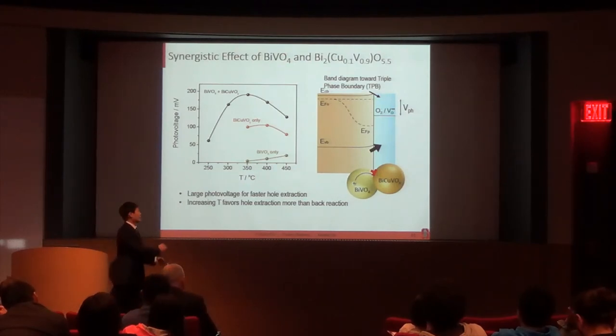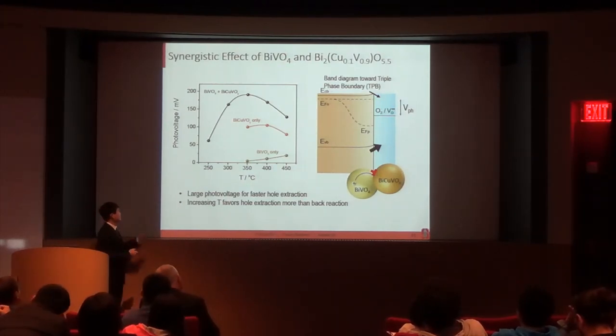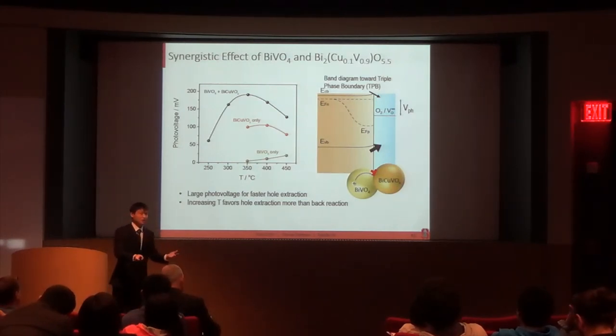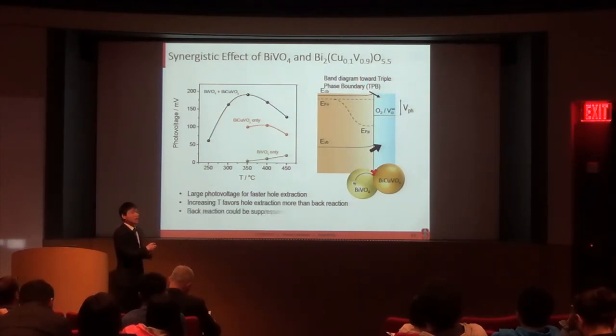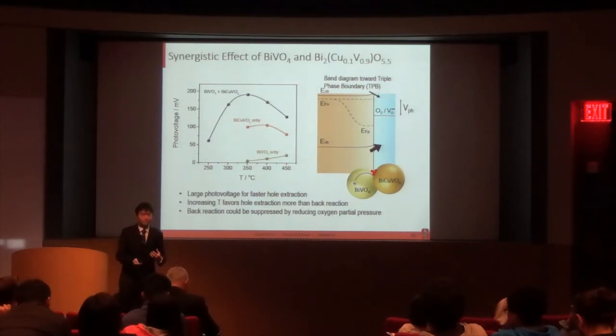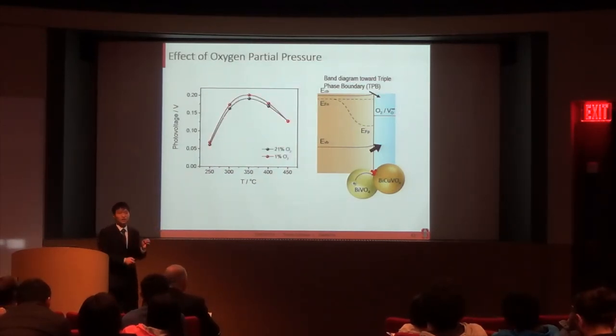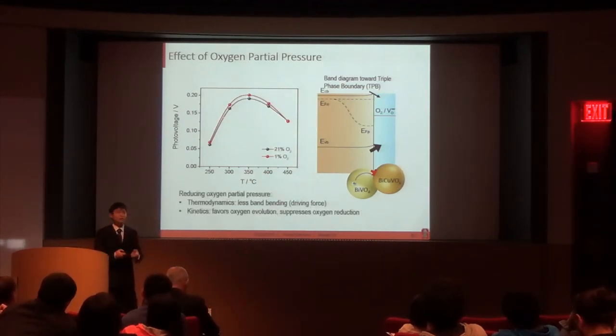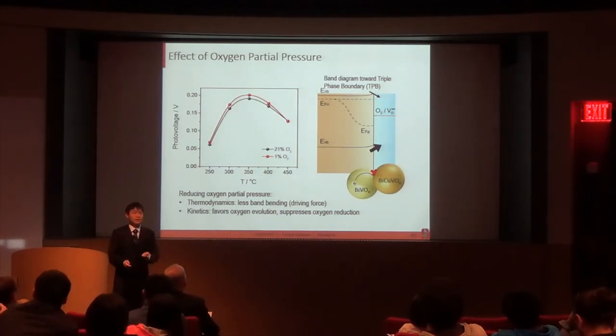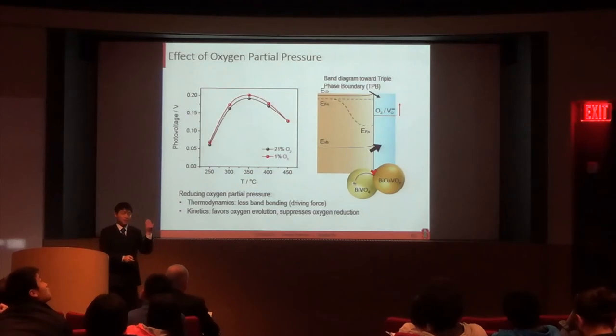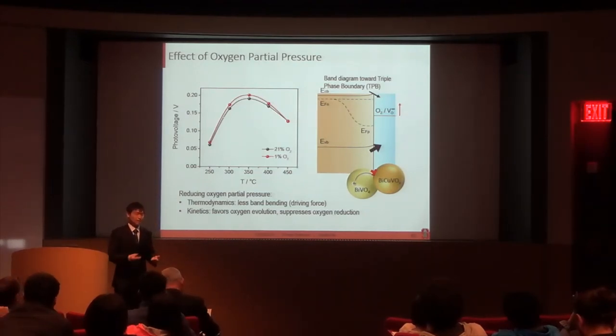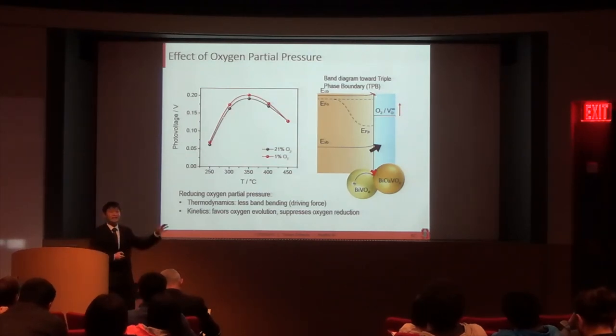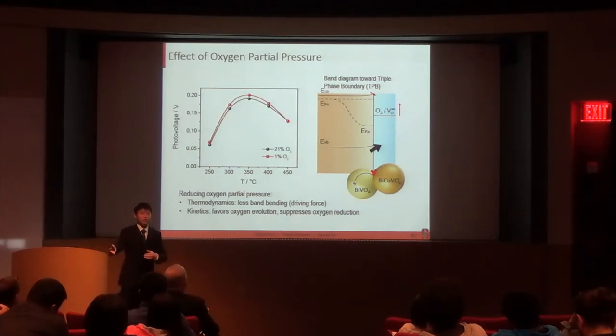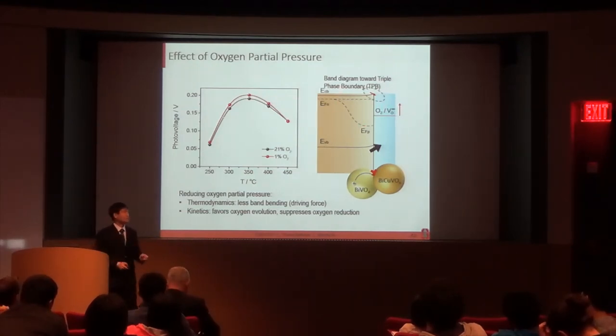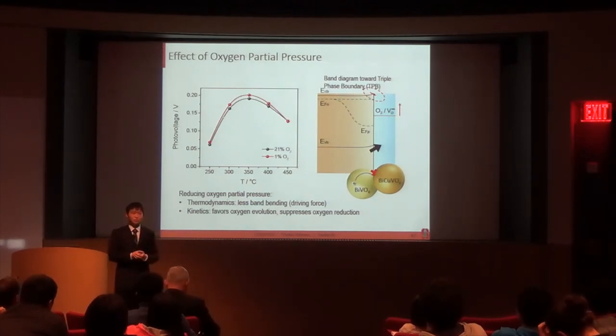So that kind of explains our thermally enhanced photovoltage, because it seems that increasing temperature favors the hole extraction more than the back reaction. And such a back reaction can be further suppressed by changing the gas environment. So we indeed observe an improved photovoltage by reducing the oxygen partial pressure. By reducing oxygen partial pressure, first thermodynamically, you're moving this redox potential upward, which causes less driving force or less band bending. So that is not good for photovoltage. But kinetically, reducing the oxygen partial pressure favors the oxygen evolution reaction while suppressing the oxygen reduction reaction, which is the back reaction. So our results suggest that the kinetics dominates the effect of oxygen partial pressure in our device.